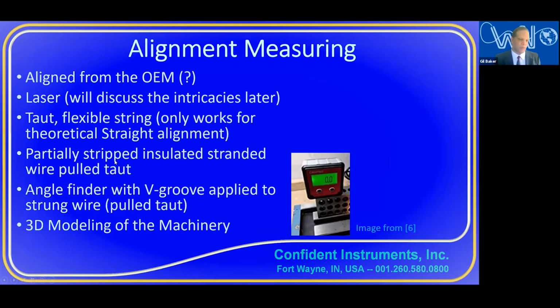You could do a similar thing with an insulated stranded wire, where you're stripping half the wire, leaving the insulation on the other. So the change from insulated wire to bare stranded wire gives you a change in diameter similar to wire drawing. Also, perhaps you could use the bare stranded wire as a continuity check between the die and the wire, such that the stranded wire will go straight through the die when it's perfectly aligned.